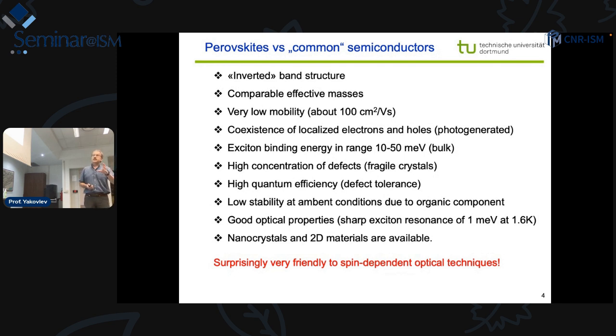But for semiconductor physics, for us, we see it. In some respects we benefit, in some respects we suffer from that. It becomes very convenient that we have a coexistence of localized electrons and holes when they are photogenerated. Again, I mostly talk about low temperature physics. The carriers are localized on the fluctuations, mobility is low, and the electrons and holes are sitting not far from each other, but in different places. They are not recombined. So if you work with such materials, you work simultaneously with N-type and P-type material. We see signals from electrons and from holes from the very same sample. We do not need to run to technologists and ask them to make a bit more N-type or a bit more P-type. The drawback is that we need to distinguish between these signals experimentally.